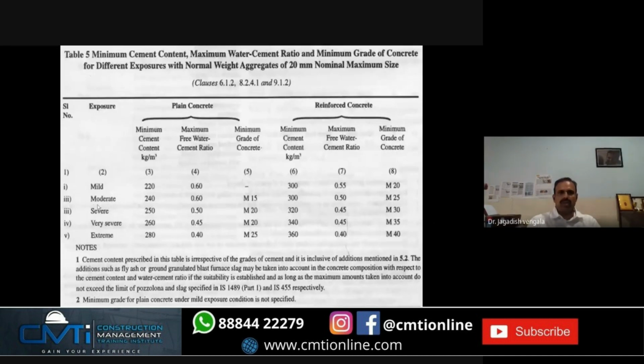Say your structure is there in severe condition. You have to maintain the maximum water cement ratio of 0.45, minimum grade M30, and you have to maintain a minimum cement content of 320. So to start with, you can design a mix by keeping these parameters into consideration. Similarly, for extreme conditions, you have to go for M40.